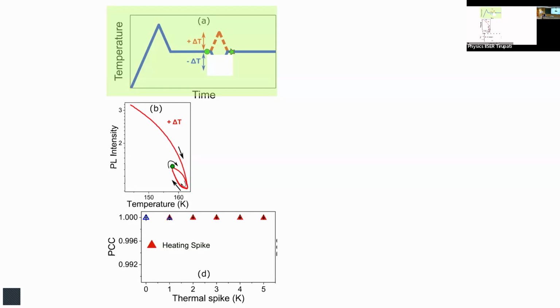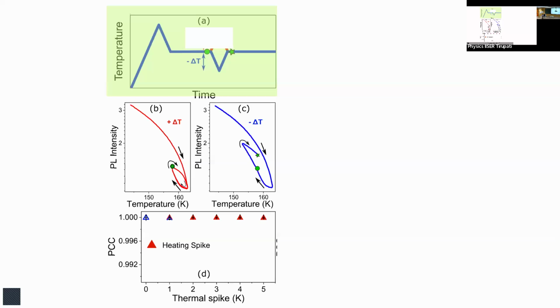But if I do the reverse one, the Pearson correlation function changes. How big the spike is doesn't matter, but if this spike is in the same direction as the thermal history I prepared, it remains the same. If the spike is in the reverse direction of the thermal history, immediately you see the spectrum is different. And the Pearson correlation function immediately deviates from 1 drastically. Though the temperature was brought back, less than 2 Kelvin, even 1 Kelvin difference, I can pick out that at some point of time, I don't know for how long, the temperature had fluctuated by 1 Kelvin down and came back to the same temperature. If I'm going the other direction, I'll simply prepare the sample the other way. That is, I'll come from high temperature, low down, and then it will be sensitive to this.